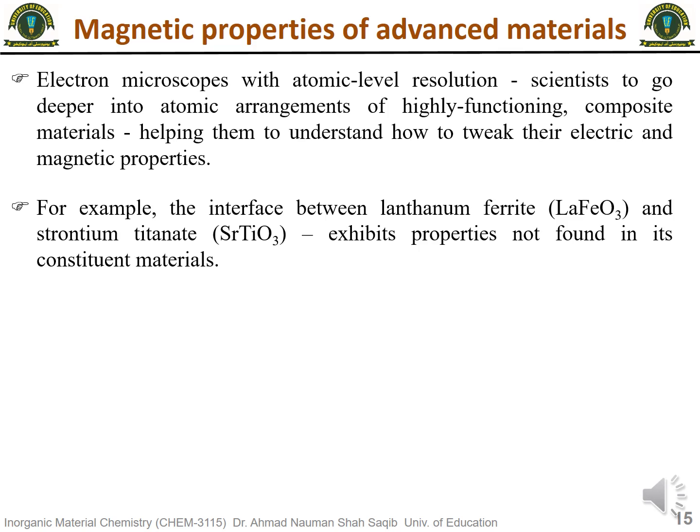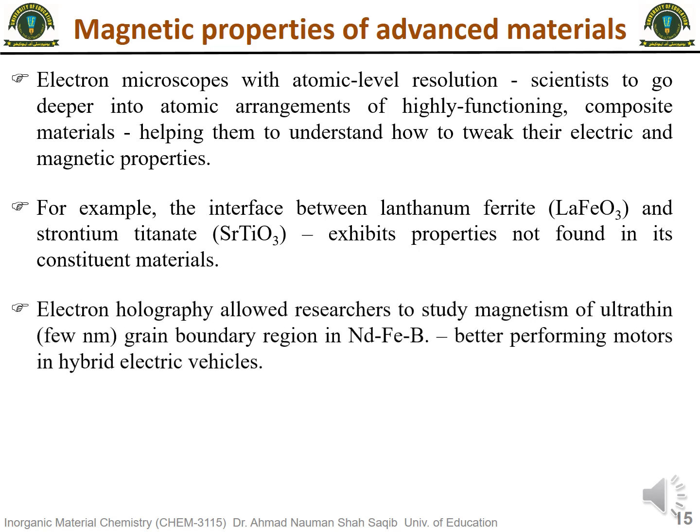Similarly, for our question of how we can improve the neodymium iron and boron composite, and how we can avoid the reduction in their coercivity at high temperature: electron holography is used by the researchers to study the magnetism of the very thin, nanometer-range grain boundary of neodymium iron and boron.